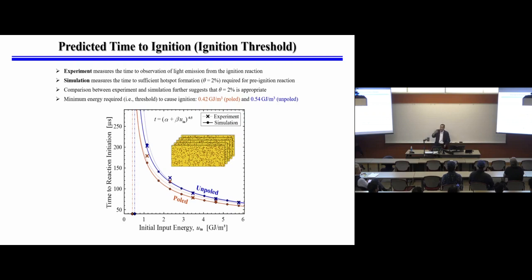So indeed, it's actually electrically driven through both piezo and flexoelectricity, and then for both unpoled and poled materials. Poled materials, again, have both piezoelectricity and flexoelectricity. Of course, it makes things happen earlier, but the difference is only about 20%. So the unpoled can almost happen as easily, and that means that flexoelectricity dominates. Piezoelectricity only helps by about 20%.